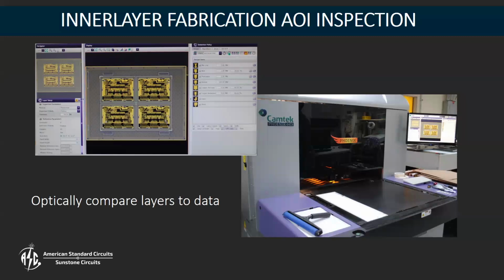basically that internal layer, those cores, and it's going to go to the next step, which happens to be an inspection step. Whether you're using AOIs or some other way of inspecting it, we're going to look at the copper that's retained on that layer and make sure that all of the signals have continuity end to end, and that the isolations are all in place. So we're going to utilize the electronic data that we created from the tooled files, and we compare on a pixel by pixel basis the retained copper on the panel to what that electronic data looks like. And anytime there's a discrepancy on a pixelated basis, that shows up as a potential defect that either gets addressed, scrapped, or repaired, or sometimes even lint or debris shows up at this point, and it's able to be removed and shown to be good product.